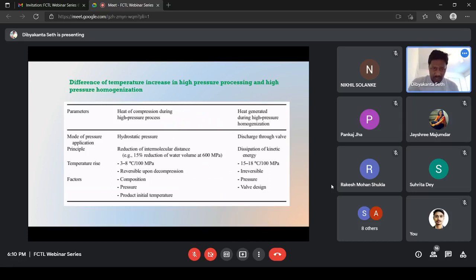Of course, heat of compression is by hydrostatic pressure, while heat of homogenization is due to the discharge through the valve. The principle is reduction in the intermolecular distance. When the intermolecular distance comes down, your heat of compression will increase. Here the kinetic energy is converted to dissipation energy. The dissipation also depends on the mechanism of action, like how much cavitation and how much turbulence there is. More turbulence means more energy dissipation into the system.